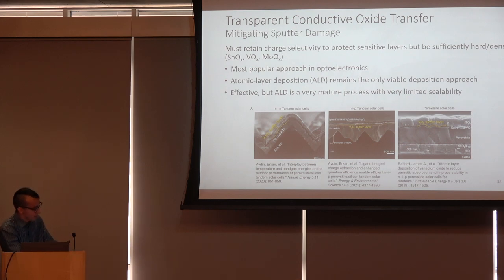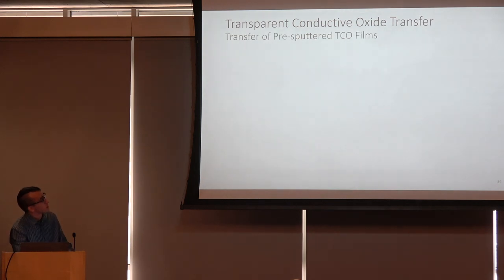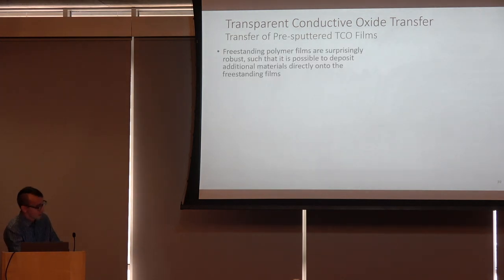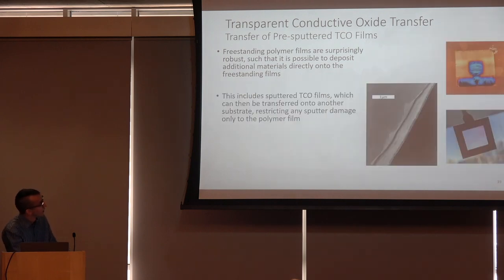This brings us to our approach. Rather than having this buffer layer to protect your perovskite, what if we don't need any buffer layer at all? We wind up sputtering our TCO directly on freestanding polymer films. And so the polymer, in this case, winds up functioning as something of a sacrificial layer. It will be subject to some amount of damage, but none of the rest of your device will be.